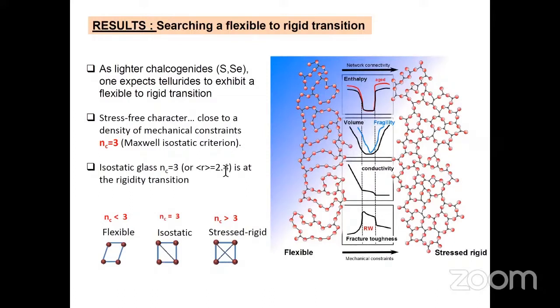So it's easy to see that if you alloy 2-fold selenium with 4-fold germanium, at some point you will reach that particular transition. So it's basically a flexible system, where the system has local deformation modes, to a stressed rigid transition, a system where you have frustration because not all bond lengths can have the same length, and the system is fully rigid because there are no deformation modes. Interestingly, you find anomalies as you go through the transition, which manifest by minima, by various extrema, or a certain number of anomalies.